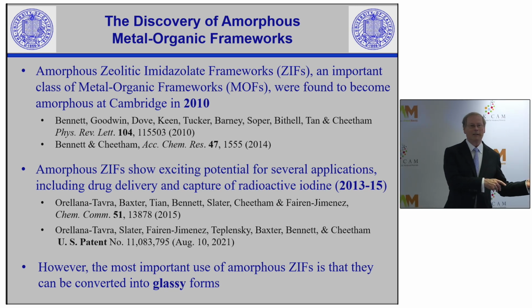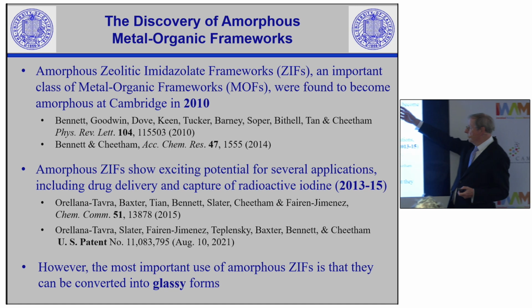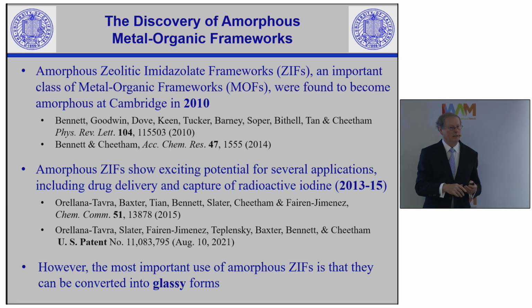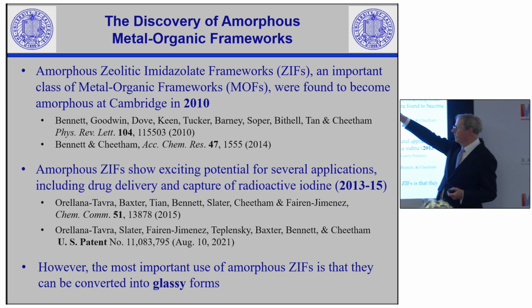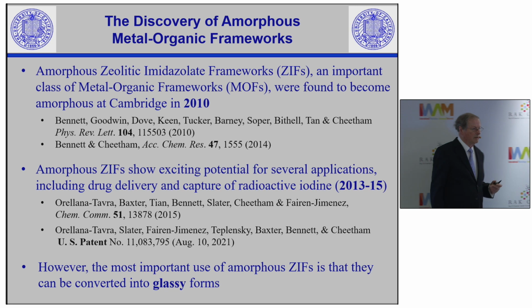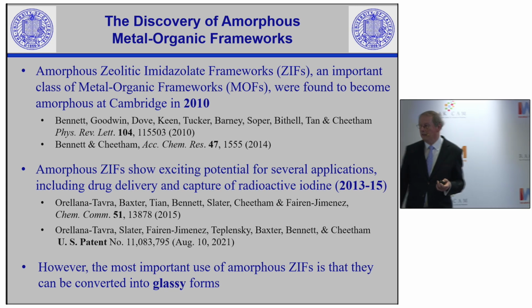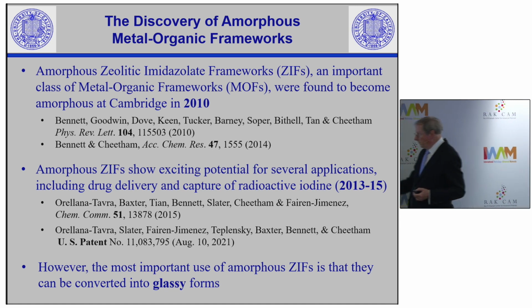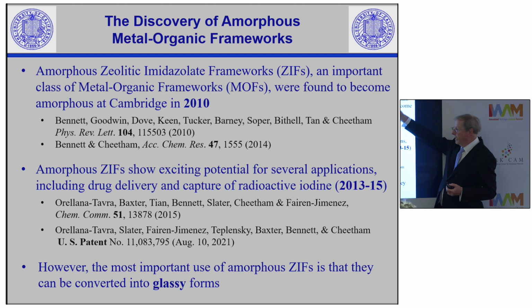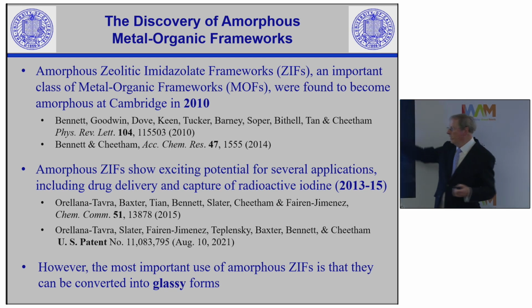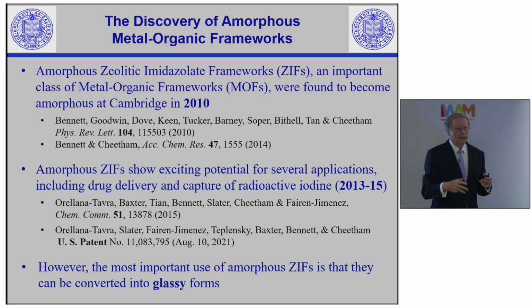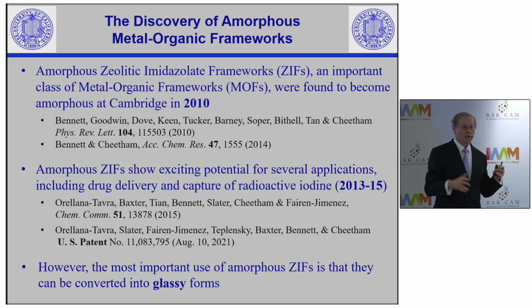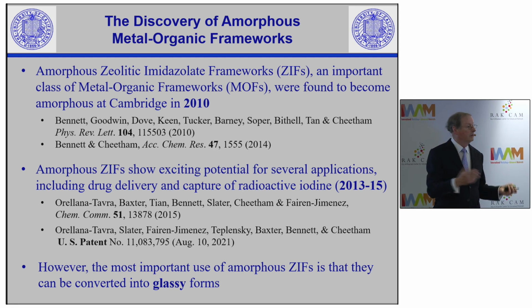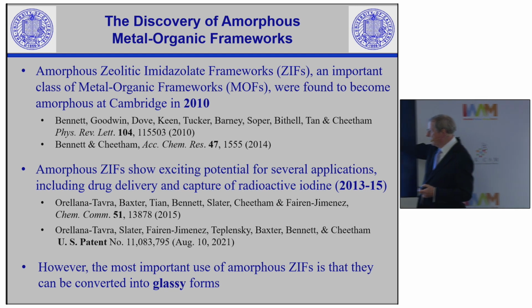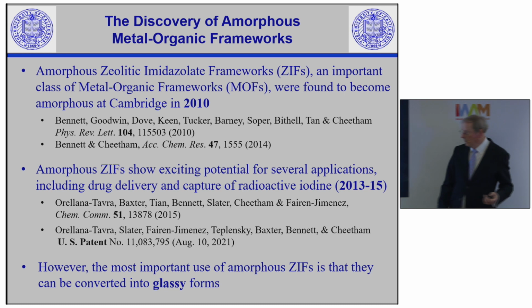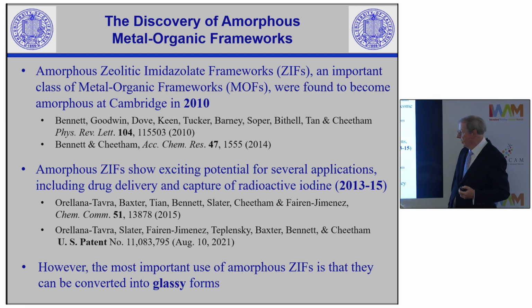Over in Cambridge, while this was going on, we were working on some metal organic frameworks related to the zeolites we talked about earlier. So they're called zeolitic imidazolate frameworks. And Mohammed knows all about these. He's done a lot of work on materials of this type. And what we were interested in is because these frameworks, which are both organic and inorganic, are related to zeolites, which are related to silica, and silica makes good glasses, we thought maybe we could make glasses or amorphous materials out of this. And one of my students, Tom Bennett, discovered this in 2010 over in Cambridge, and we wrote an article.